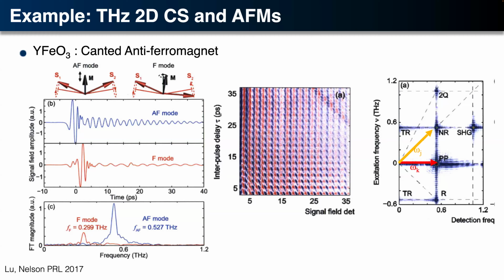But if I have a nonlinear response, there are many potential paths that I could excite. And each of those paths, the chemists would call these Liouville pathways, encodes different information about the material system in a way that I couldn't get otherwise. They show up in different places in the 2D plot. And in this response, we always have to have three fields involved. The different fields appear as colored arrows, of which I won't explain the details. But that's like one field of A and two fields of B bring me to a position right there.